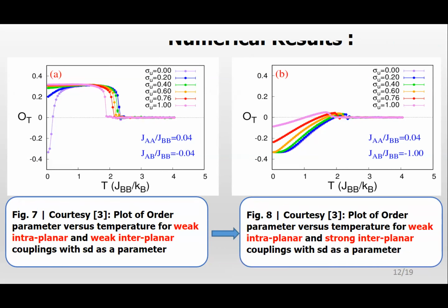These are the two plots of order parameter versus temperature. In figure 7 at left, we see compensation is present when there was no applied field. Please see the purple curve. But for all the non-zero values of the field, compensation is destroyed, and even the magnetization at the lowest temperature is affected. In figure 8 at right, when the antiferromagnetic coupling ratio is decreased from minus 0.04 to minus 1.0, we see the system shows compensation for zero and non-zero fields, but the magnetization of the bulk at the lowest temperature and the nature of evolution actually changes.